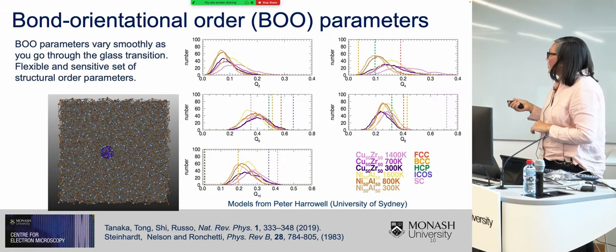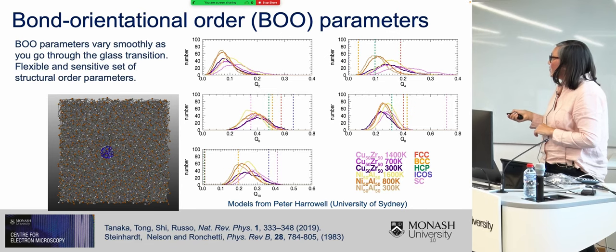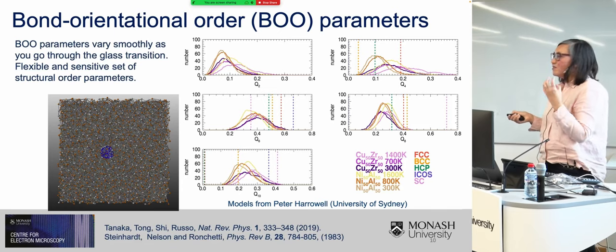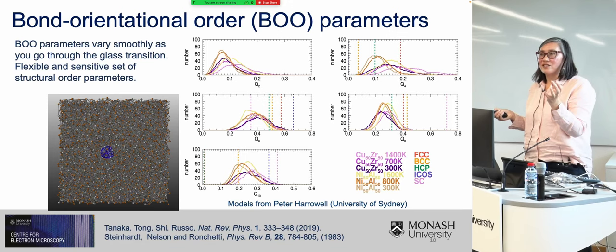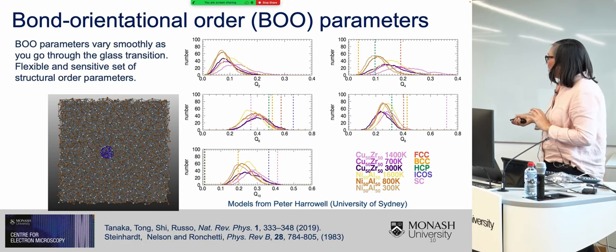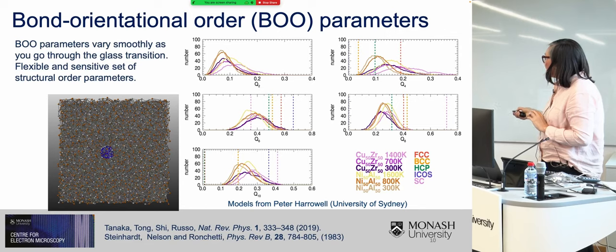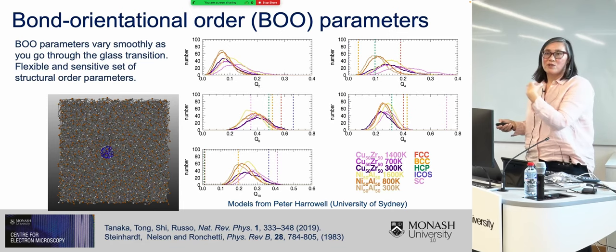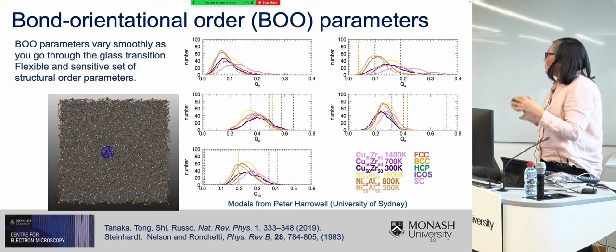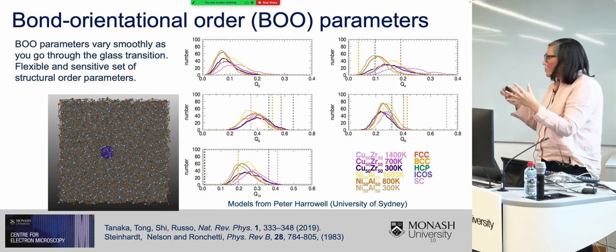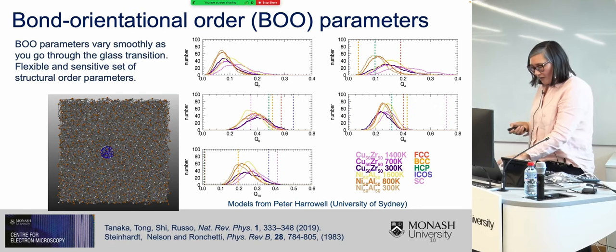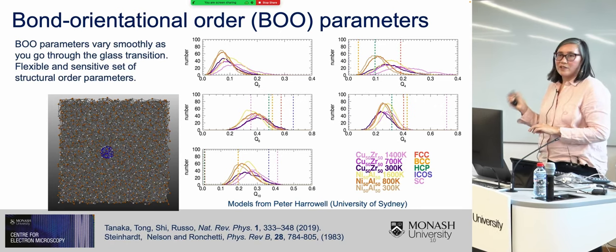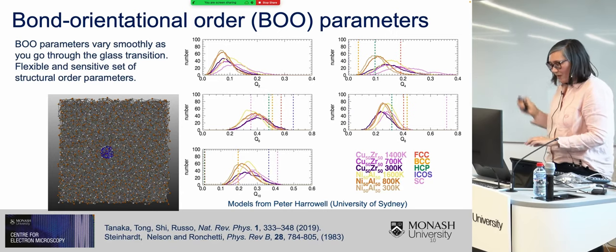And the other problem with these BOO parameters is that even though they are a flexible and sensitive set of local structural order parameters, they don't really capture what's going on at the glass transition. You can see here, these are calculations I've done from models from Peter Harrowell in Sydney. For these different metallic systems at these different temperatures, the distributions of these BOO parameters actually vary somewhat smoothly. So while they are sensitive and flexible, they don't seem to be capturing what's going on at the glass transition. But I will, however, note that no other structural parameter has been able to capture that, which is part of the problem.